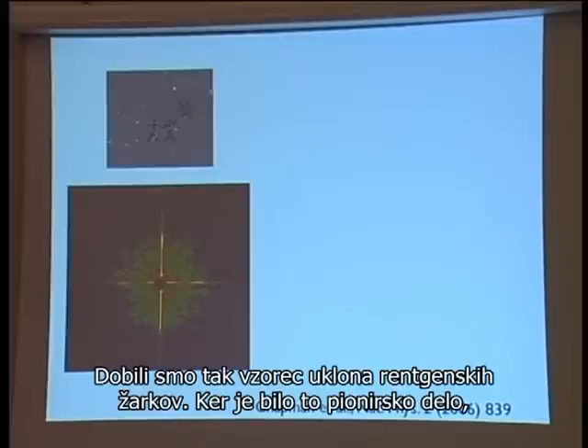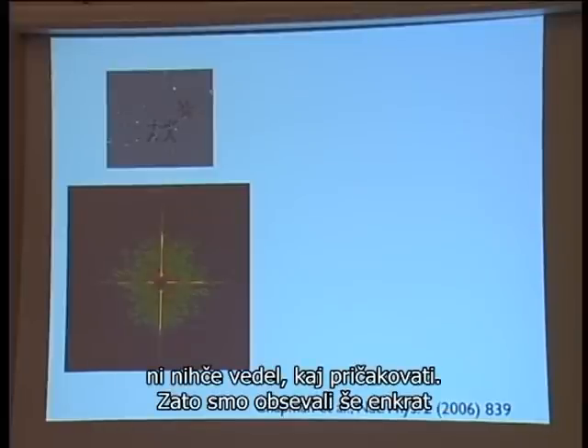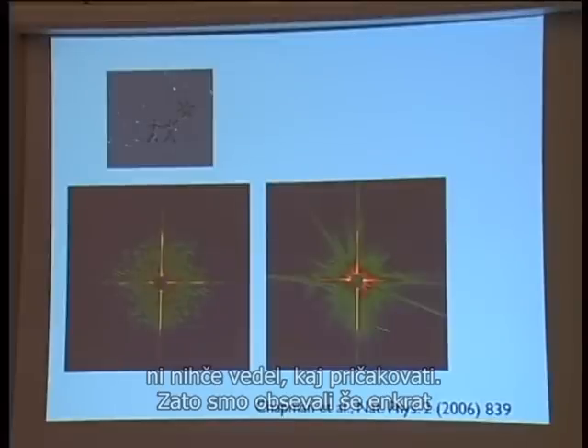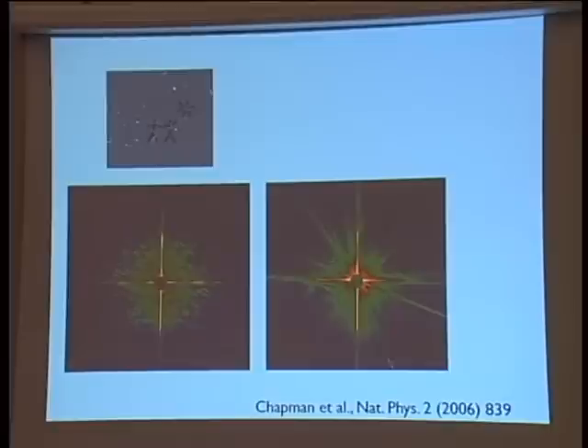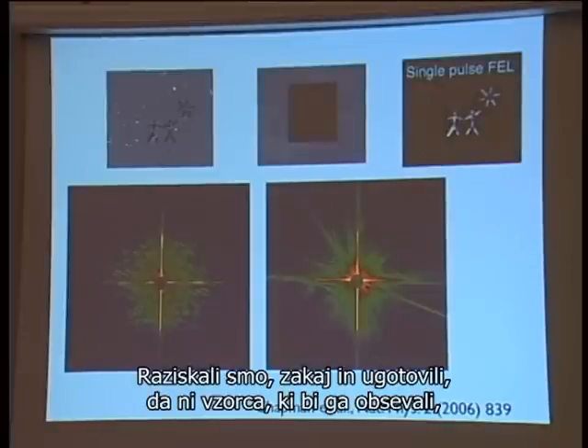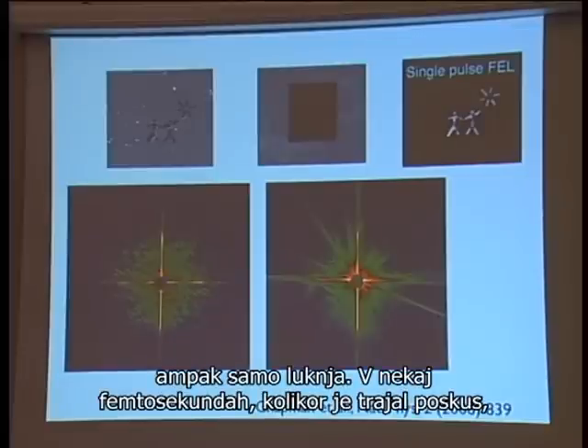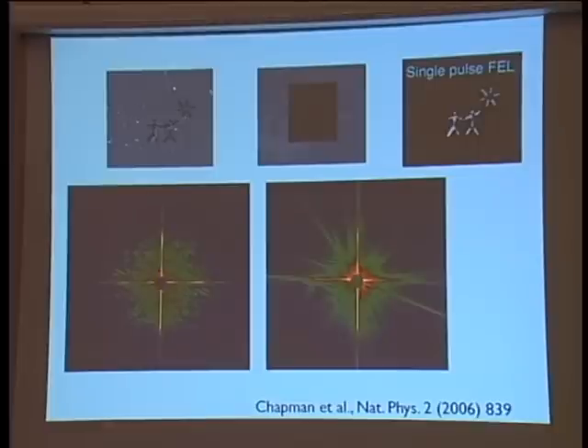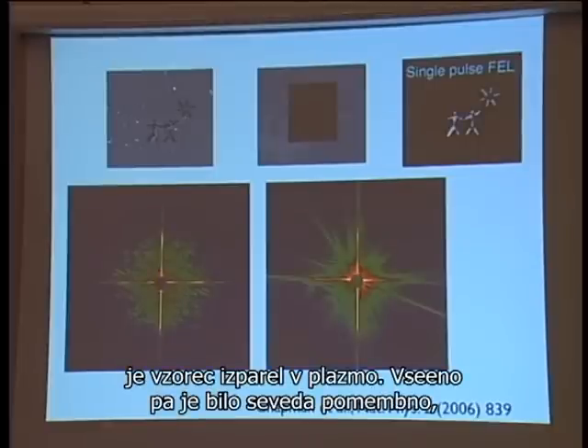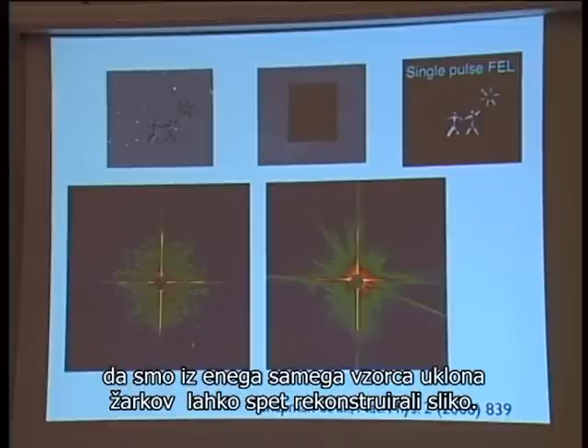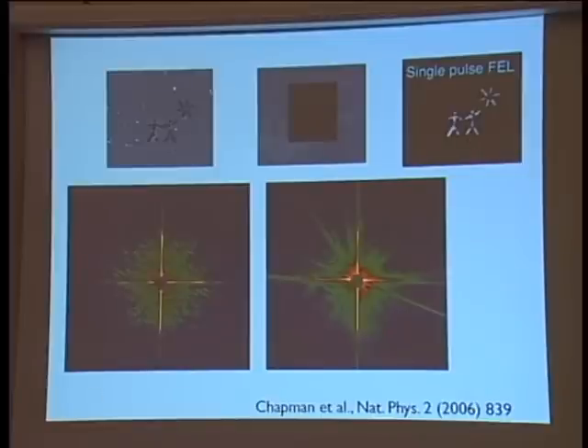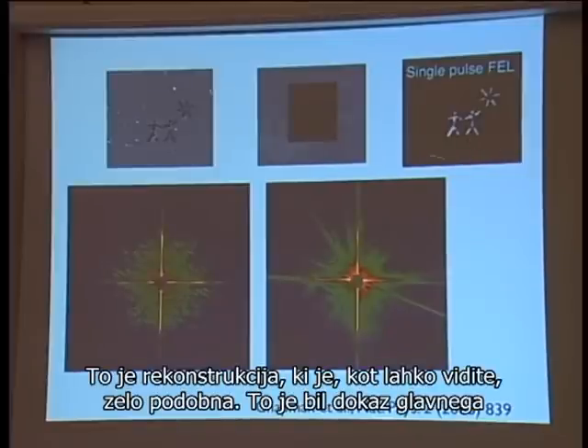Since this was pioneering work, no one knew what to expect. So we shot again, and the diffraction pattern looked like that, obviously different. So we looked at why, and there was no sample there. There was just a hole. Within a few femtoseconds, whatever it took to do this one shot, the sample evaporated, turned into plasma. Nevertheless, what was important is that from this single diffraction image, we were able to reconstruct the picture again. This is a reconstruction, which looks, as you can see, very similar.